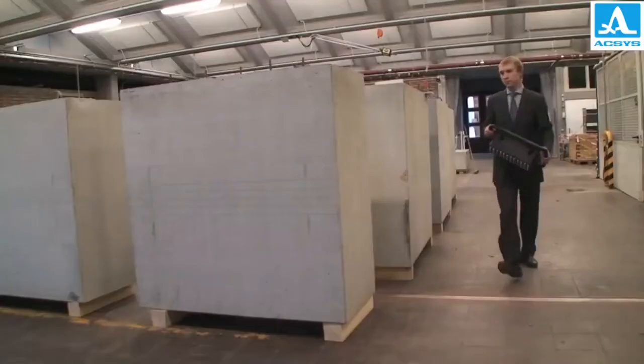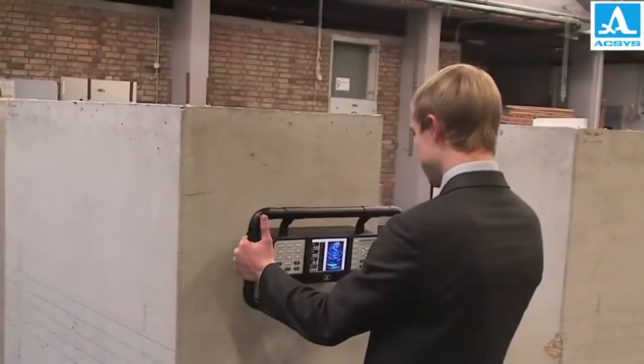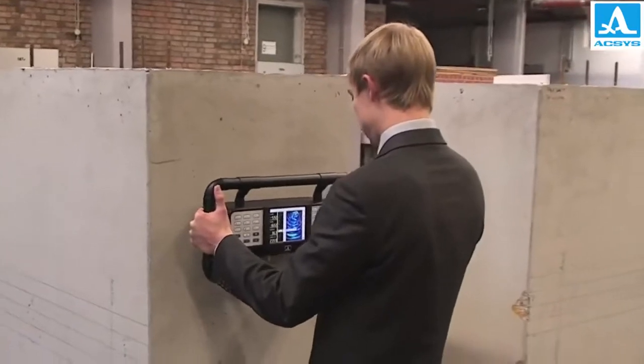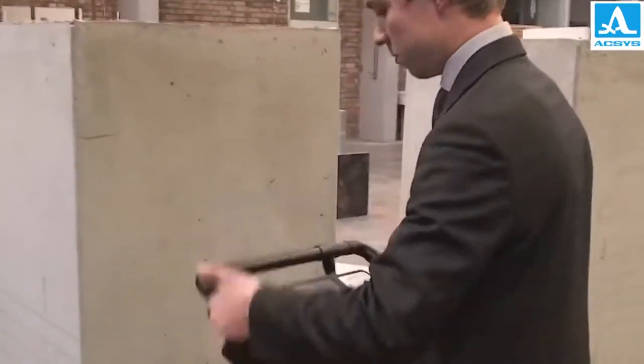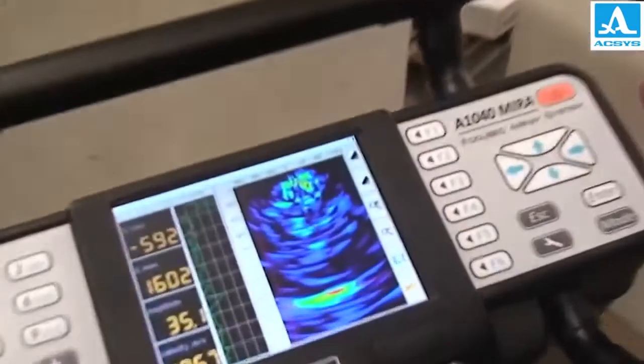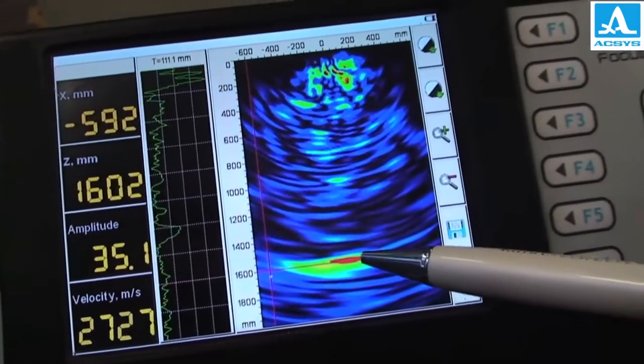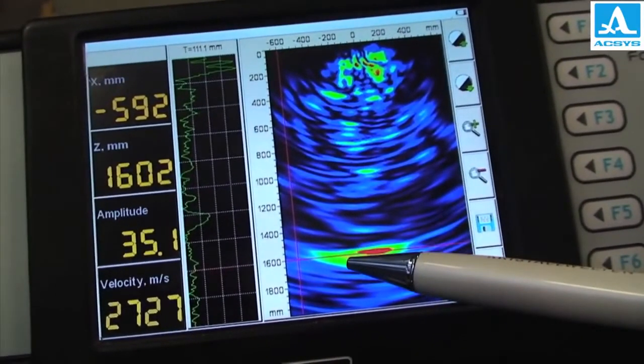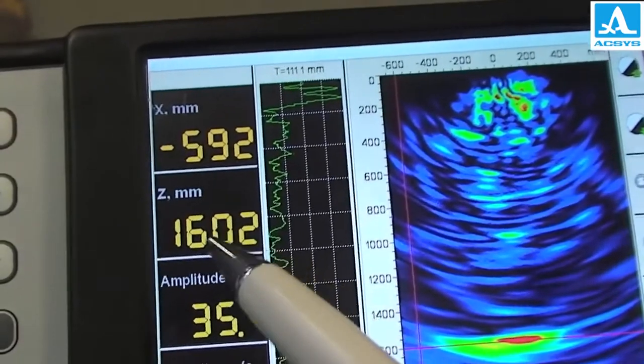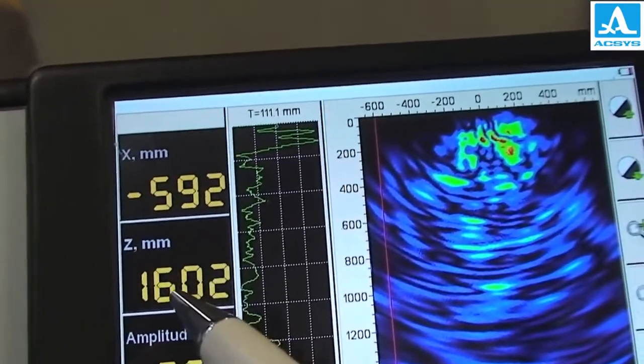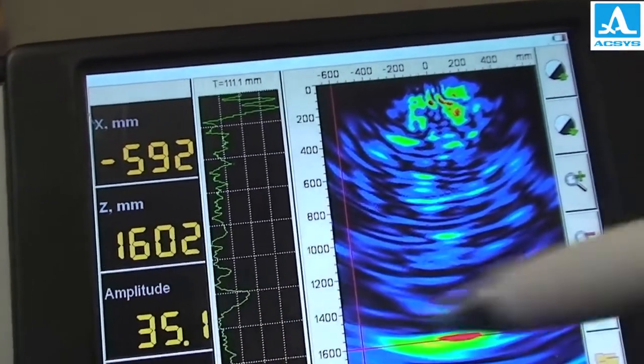Ultrasonic testing of a concrete wall panel was performed using the mirror system to measure the thickness of the wall. At about 3 to 4 seconds after the system was triggered, the test results were displayed on the built-in screen. The bright red area in the tomogram corresponds to the signal reflected from the back wall. The thickness of the concrete wall panel is indicated by placing the cursor at the center line of the red spot and reading the corresponding depth on the metric scale on the left side of the tomogram.